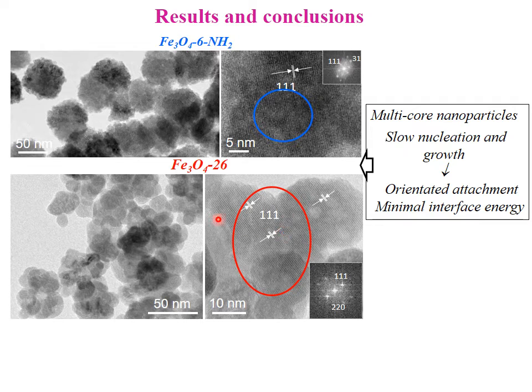In the 26 sample, the role of ethylene glycol is also as reductor, but it is a weak reductor, and the growth is slow. In both cases, the nanoparticles have enough time to rotate, and most of them in the assembly have the same crystal orientation, minimizing the surface energy.